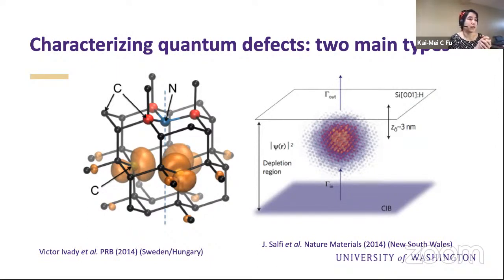The other type of defect is the Wannier exciton. And this is a defect where the localization is spread out over many lattice sites. So on the left is actually the NV center orbitals. On the right is a reconstruction from an STM measurement from a silicon group, and what you see is actually the wave function of a phosphorus donor in silicon in this case. And you can see that it takes many lattice sites. In this particular defect, you use effective mass theory. In fact, many of the properties of the defect, the optical properties, actually come from the band structure of the crystal.